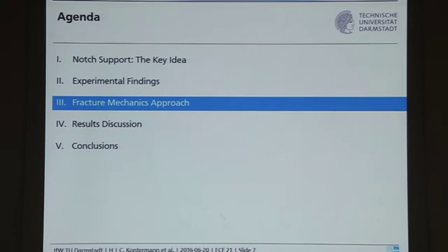And we have here short cracks, so our plastic zone size is not comparably small. And the third constraint is we will not rely on any analytical solutions, because we would like to apply these concepts to components. And due to the limited application range of these analytical solutions, which are available for certain standard models, this is a difficulty, and so we would choose to exclusively use the finite element method in order to simulate plasticity-induced crack closure, as well as to simulate an appropriate crack tip parameter, like delta J.